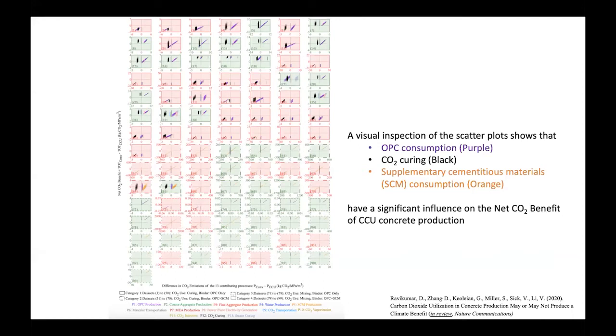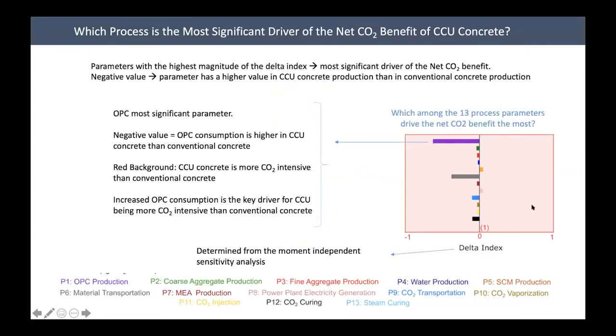So we went a step ahead and conducted a moment-independent sensitivity analysis, where we calculate a delta index value for each of the 13 parameters. As you can see here, this is how we interpret this graph. The parameter with the highest delta index, calculated using a moment-independent sensitivity analysis, has the greatest influence on the net CO2 benefit. As you can see here, purple has the highest value. So that means OPC consumption has a significant influence. And if it is in the negative x direction, that means the parameter value is higher in CCU concrete when compared to conventional concrete.